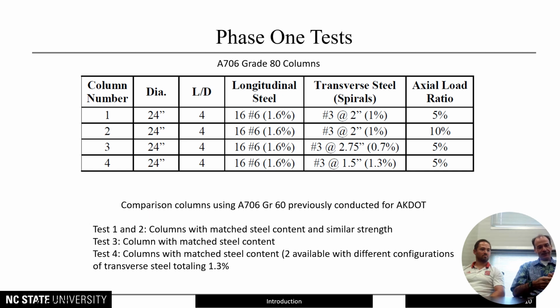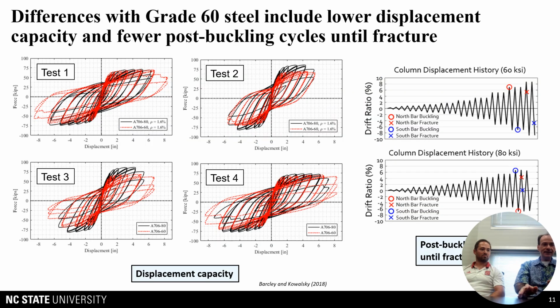And we did four column tests at that time, and we varied reinforcing steel ratio and transverse steel ratio, axial ratio, to try and get a cross section of different design parameters. And those tests, the force-displacement responses were shown here, and you can see the behavior. The red is the Grade 60 columns, or the companion columns, and black was the tests that Leo did, the ones with the high-strength steel.